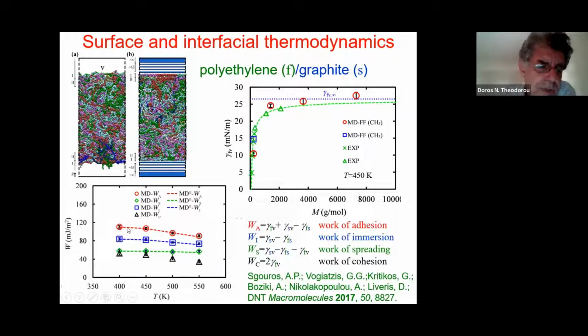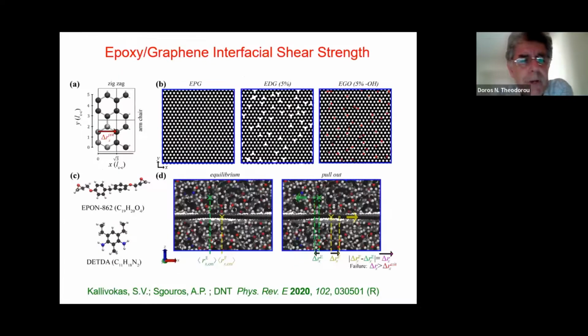And what you see with the broken lines is an approximation to these properties based on the so-called Girifalco and Good expression, which claims that the work of adhesion should be 2 times the square root of the product of the surface free energies of the polymer and the solid. And it works very well in these cases because the interactions are of a London dispersion type.